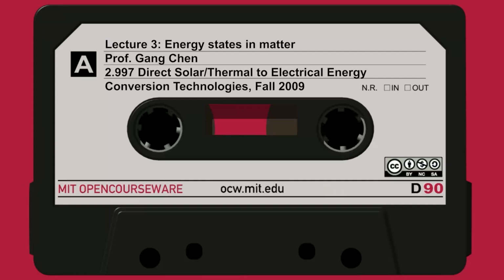And the Boltzmann statistics is only valid when this mu is far below EC. Once mu gets into here, you have to use the Fermi-Dirac statistics. That's a degenerate semiconductor. This is the only approximation. But here it is general. You can always do that math to invert and, for a given number, get the chemical potential.